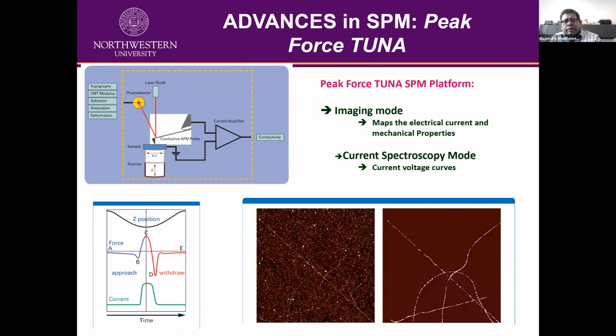So having said that, then we have PeakForce TUNA, which is tunneling AFM, or tunneling current measurements. You can see here on the bottom left in the figure, usually we use a typical conducting AFM probe. And in traditional conducting AFM imaging, the tip was putting a lot of force on the sample surface. These cantilevers are coated with thin metal layers. And when the cantilever interacts with the sample surface and applies a large force in contact mode, the coating rips off. And it's pretty troublesome: in the middle of your experiment, your coating is not there and you're not getting your image. So that was a problem.